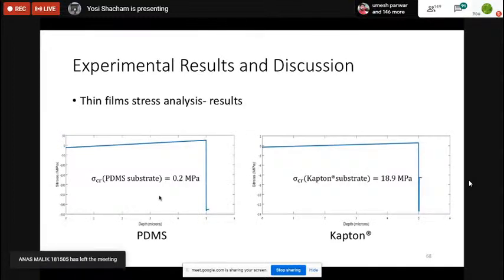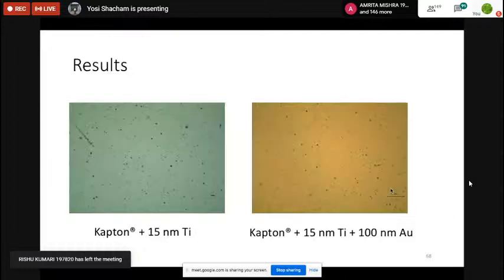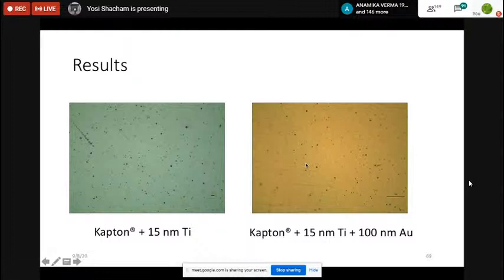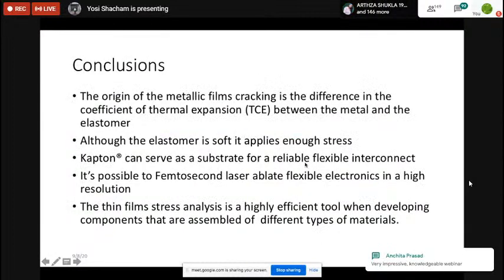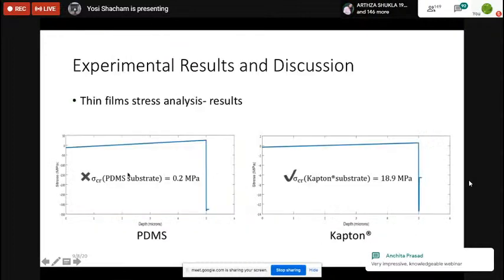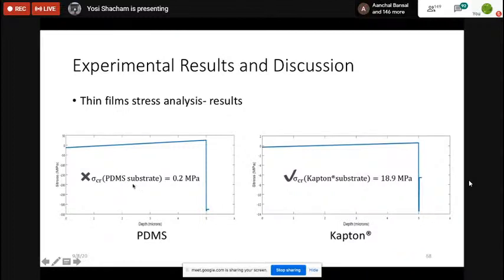And the critical stress for PDMS is 0.2, and for Kapton is 18.9, which means, first, we found out that if we deposit it on Kapton, no cracks, nothing. Or alternatively, we change the composition of the PDMS to increase the Young's modulus of the PDMS and to reduce the coefficient of thermal expansion. And then we solve the problem.